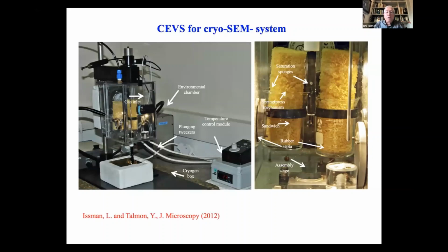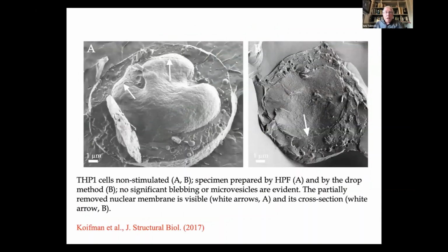Again, without going into details, more than 10 years ago, we were able to develop an analogous controlled environment vitrification system for Cryo-SEM, which means that we can prepare the specimens under controlled conditions of temperature and humidity in order to avoid any loss of volatiles from the specimen. And just two examples, and this goes back to a paper by Naama Koifman, who is in the audience now.